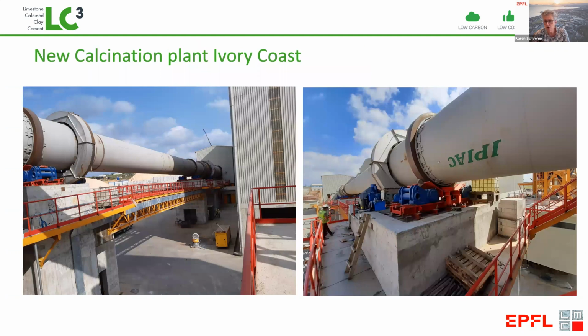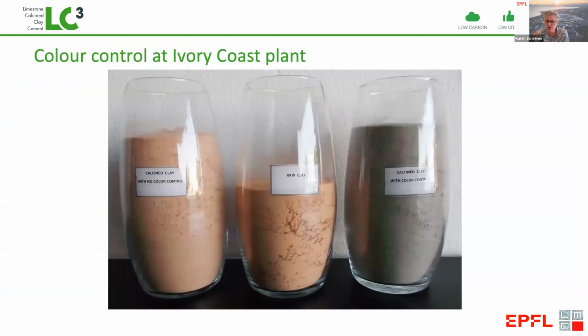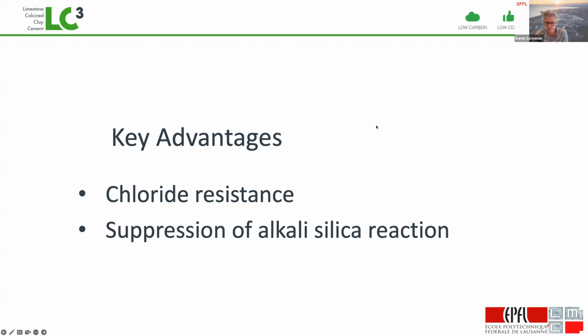And here we have one of the first full-scale plants, which is set up in the Ivory Coast. Now, this plant in the Ivory Coast demonstrated another important criteria, which is the ability to control the color of the clay. So people are used to having gray cement, and for some people, the idea of having a kind of pink or red cement is not very nice. But with a very simple technology coming from the brick industry, you can make the clay gray.